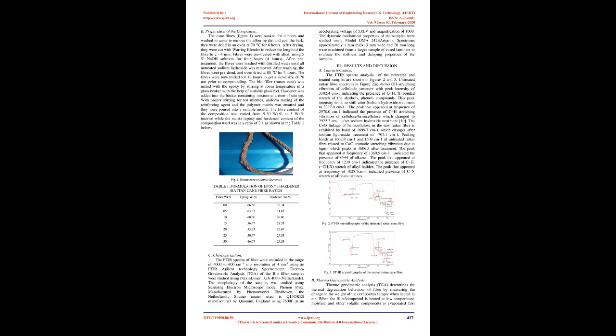After washing, the fibers were pre-dried and oven-dried at 80 °C for 4 hours. The fibers were ball milled for 12 hours to get a sieve size of 70 μm prior to compounding.